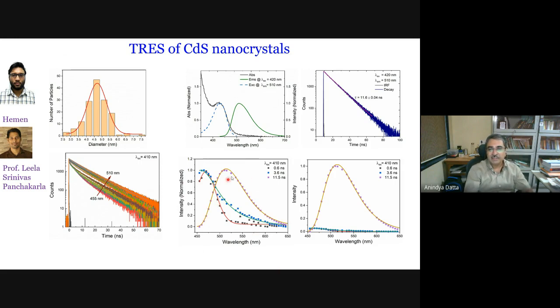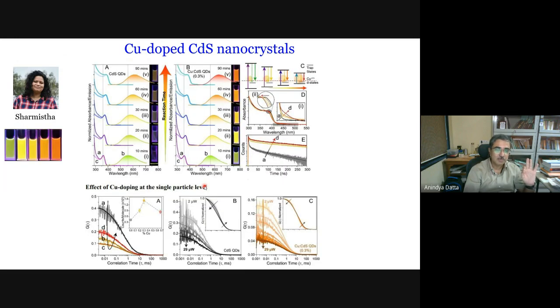The long component, 11.5 nanosecond, gives us a spectrum that is exactly the same as the emission spectrum, the steady state spectrum. However, if you look at the short component, 0.6 nanosecond or so, we get a significantly blue shifted and narrower spectrum. That could be the band edge emission. It's possible that other phenomena are involved here, but it could be band edge emission as well. So this is something that we are trying to probe.